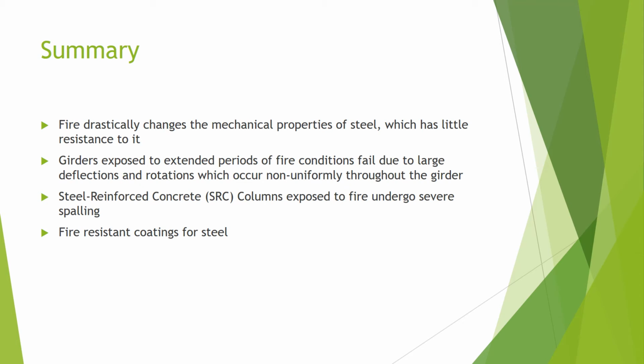In summary, fire drastically changes the mechanical properties of steel. Steel has little resistance to excessive heat. Girders exposed to extended periods of fire conditions fail due to large deflections and rotations which occur non-uniformly throughout the girder. Steel reinforced concrete columns exposed to fire undergo severe spalling, and fire-resistant coatings are sometimes used to minimize the effects that high temperatures have on steel.